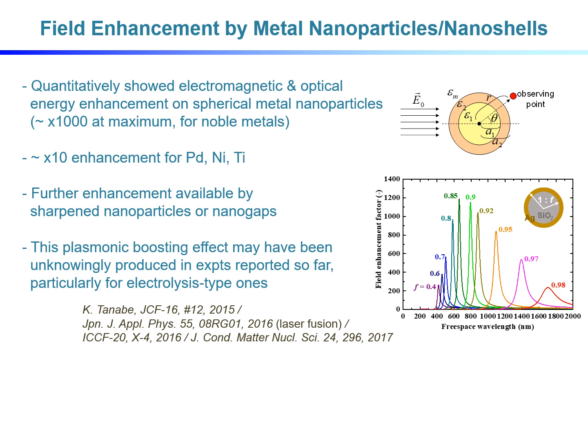We quantitatively showed the electromagnetic and optical energy enhancement effect on spherical metal nanoparticles and nanoshells, with peak enhancement factors of about 1000 for noble metal nanoshells and about 10 for the transition metals commonly used in the community. Here, we calculated for spherical particles and shells for simplicity, but further enhancement is available by sharpened nanoparticles and nanogaps, as I will present later. Such a plasmonic boosting effect might have been unconsciously produced in the experiments reported so far in the community, particularly for the electrolysis-type ones with applied electric field.